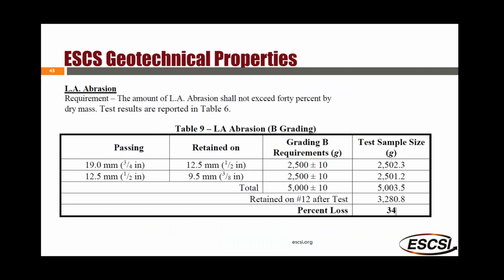The material is very durable. LA abrasion results for this particular sample was 34% loss. It's common to see AASHTO specification requirements of no more than 40% loss. So this ESCS material would fit in that category very nicely.